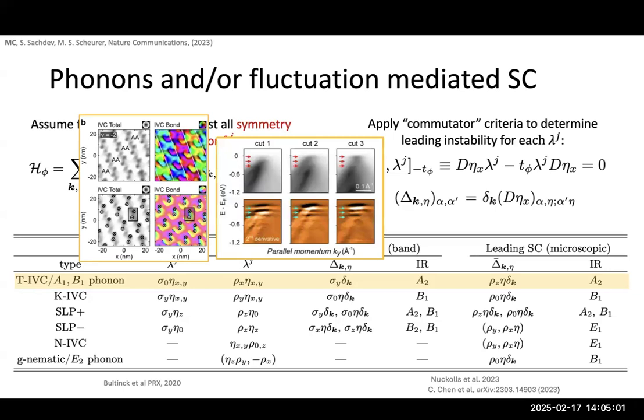And then another reason to consider this type of boson is that a different group measured, in photoemission experiments, replica bands of these 2 flat bands, where the energy spacing is roughly the phonon frequency of these A1, B1 optical phonons. And so it's believed that these phonons may be strongly coupled in TBG. And they only measure these replica bands when the sample is not aligned with hBN. And so hBN, which kills the superconductor, also seems to kill this coupling they see. So this is a twofold reason to focus on this type of fluctuation.